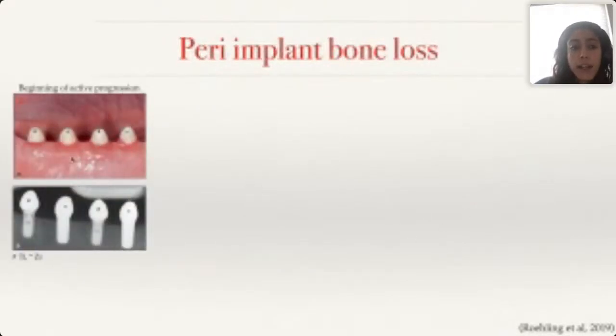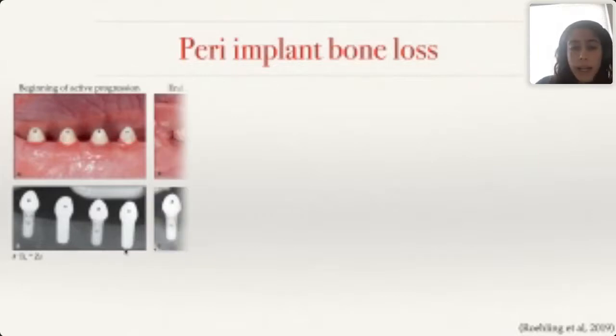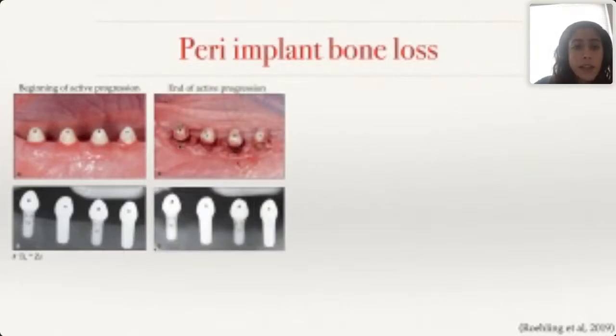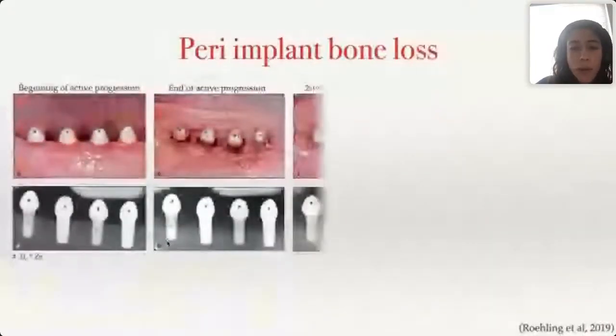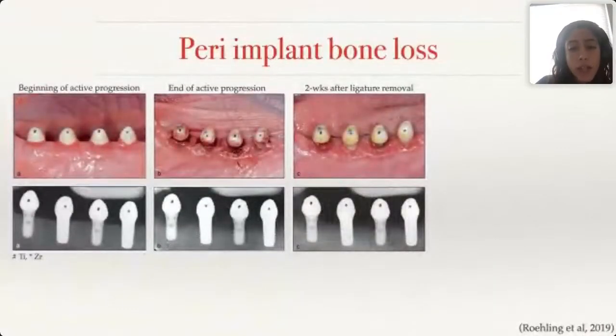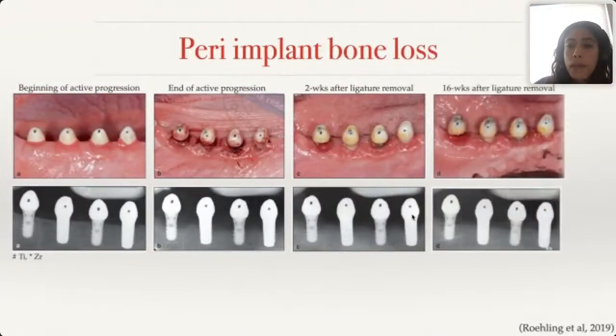This is at the beginning, where they placed the cotton ligatures - these are the titanium implants and these are the zirconia implants. Here the ligatures were removed, and we can see the bone loss, pretty extensive on this sample - they actually lost one titanium implant in the group. This is 2 weeks after ligature removal, and then 16 weeks after ligature removal.